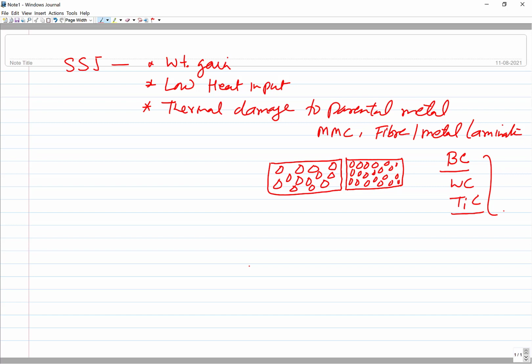So what is happening when we use a high heat input process like fusion welding is that we have to bring all these to the molten state, and when it is done, you will find that all the reinforcing agents get thermally damaged very badly. They will get decomposed, brought to the molten state, and lose their identities. Similarly, the regions which are very close to the fusion zone, or in the heat affected zone, which are subjected to very high temperature, the metal and reinforcing agent characteristics are also adversely affected.